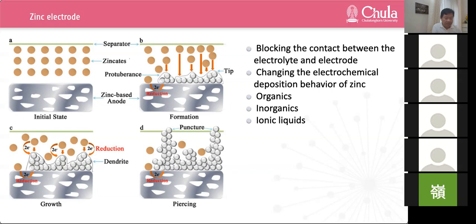And the active components in the electrolyte are more likely to diffuse to protrusions on the electrode surface, where the current density is much higher for reaction, resulting in uneven current distribution on the electrode. The deposition of zinc is sped up on the tip of the electrode to form eventual dendrites. During the charging process, the deposition morphology of the zinc electrode varies with the current density.